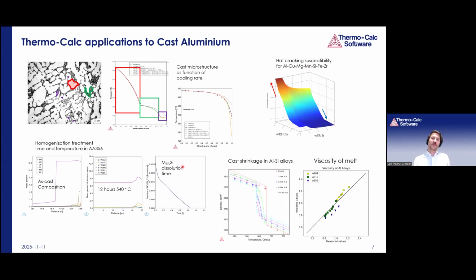And also some important properties to the casting and melt properties. The cast shrinkage, so the increase in density or the decrease of volume during solidification, or the viscosity, for example, here for a couple of different cast alloys. Very important for the behavior of the melt, the flowability and so on.